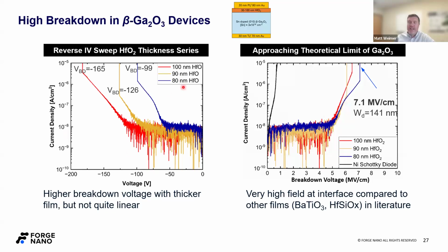So if we start on the left here, we did a thickness series of 80, 90, and 100 nanometers. You'll notice that our leakage current is much lower, about 2 orders of magnitude lower. So again, that interface is critical, right? We also see that, roughly speaking, the breakdown gets higher with higher thickness. But when we normalize for thickness and look at that breakdown field, in megavolts per centimeter, the best performing was actually 80 nanometers. Not exactly sure why, but it's very interesting. This is quite impressive. We're getting close to that theoretical limit of what gallium oxide can do. So I think there's a lot of potential here in using hafnium dioxide as a dielectric.